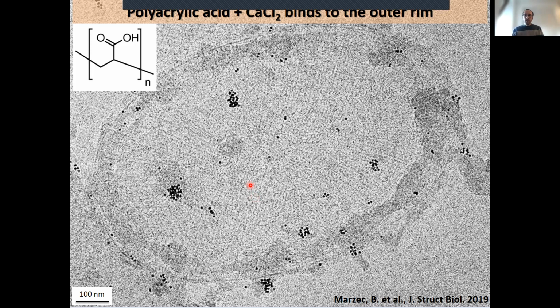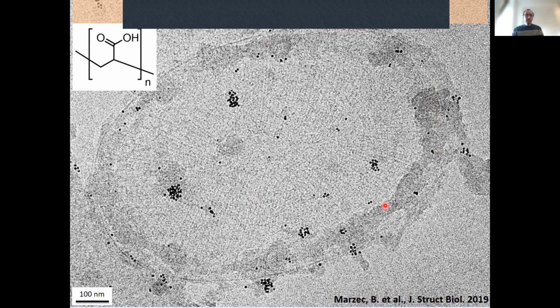cryo-TEM image, that when you mix polyacrylic acid with calcium chloride, now we're using polyacrylic acid, it's highly acidic. Polysaccharides are also highly acidic. The coccolithophore polysaccharides are highly acidic, so it's a suitable mimic in that sense. And it forms complexes with calcium ions, and then it binds to the rim of the base plate.